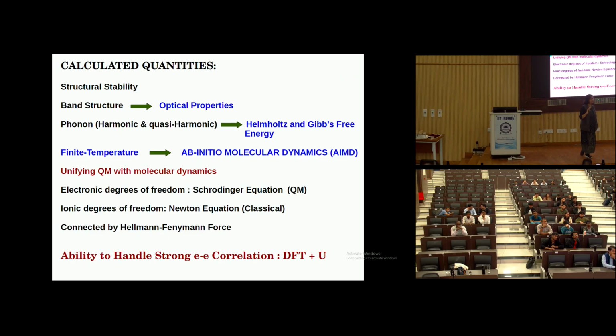Since many of you are masters in physics, you know what a phonon is, a lattice vibration. If you can calculate the total energy, then with the displacement of the ions I can recalculate those energies, and that gives me the dynamical matrix. If we diagonalize that dynamical matrix, I get the phonon modes. So if you know the phonons, you can calculate the Helmholtz energy and the Gibbs free energy. For the Gibbs free energy, you need a little more information: you also need to calculate exactly how the phonons change as the volume changes. But phonons you can calculate, and therefore in some way you have access to free energy.